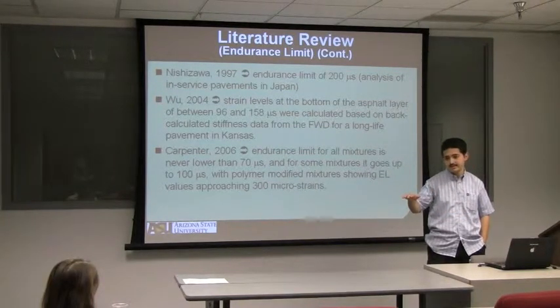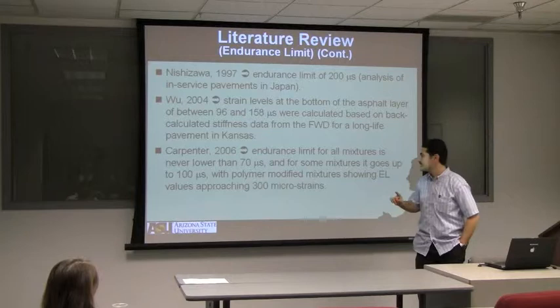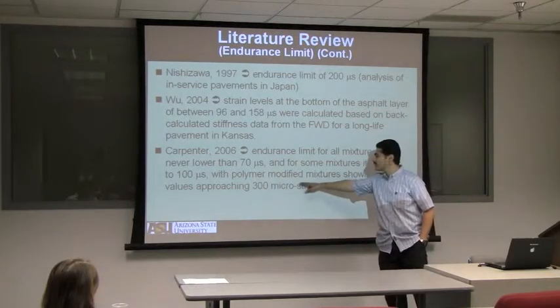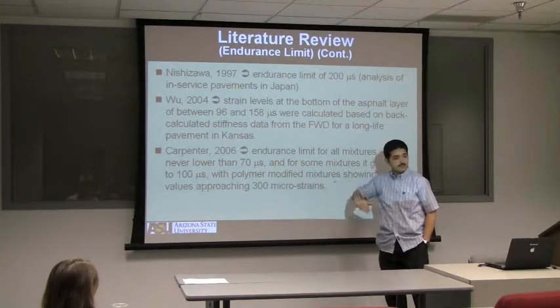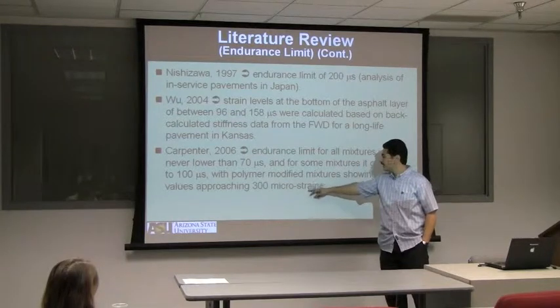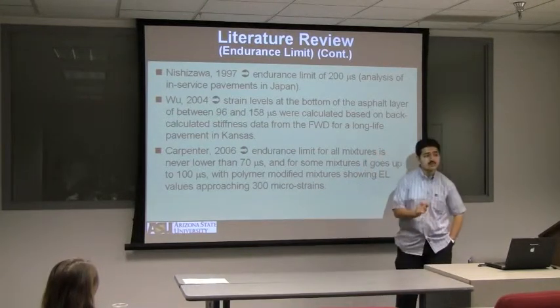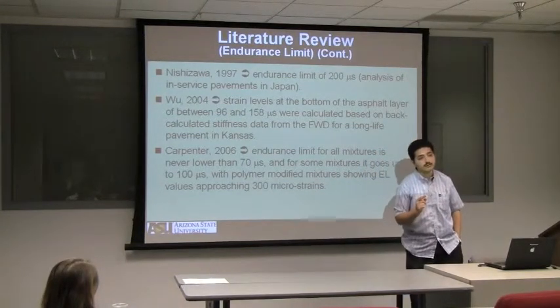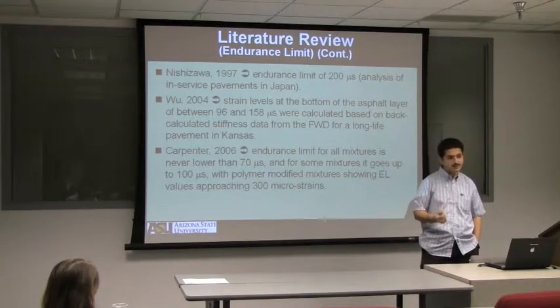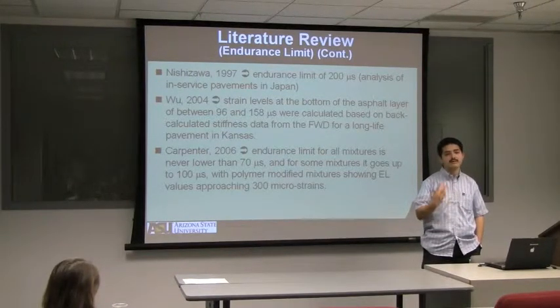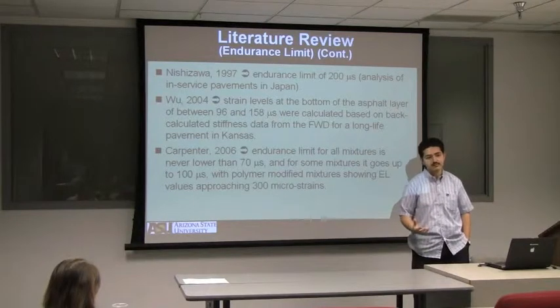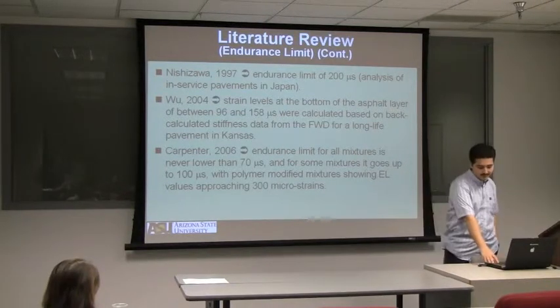Carpenter in 2006, he reported that the endurance limit is about 70 microstrains, and it can go to 100 microstrains in certain cases. But what is interesting in his recommendation here is that the endurance limit can be pumped up all the way to 300 microstrains once you modify your mixture by adding polymer or by adding asphalt rubber. So this here starts to show that the endurance limit can change or can improve by modifying the asphalt mixtures that we have been using in the last 100 years.